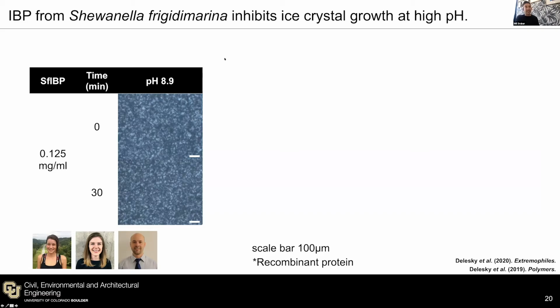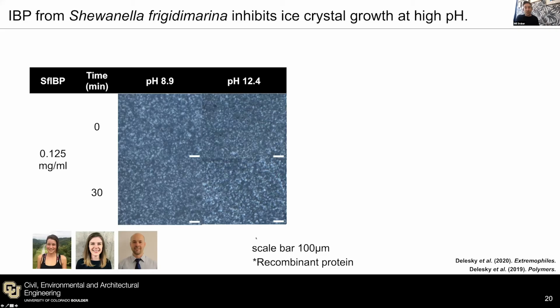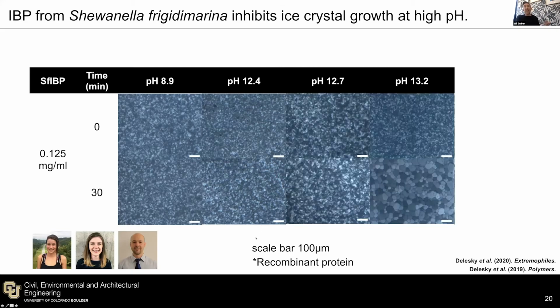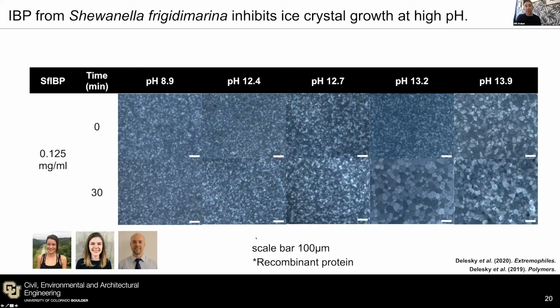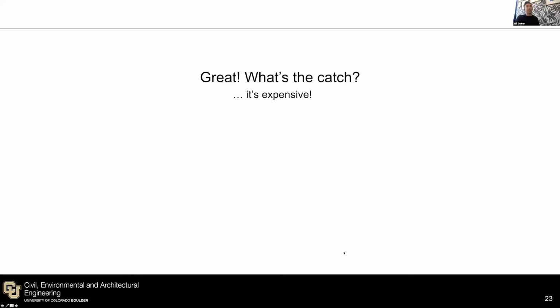We were exceptionally excited to see it maintained that activity at pH 12, pH 12.7, but then after we reached a certain threshold, what we proved in these papers is that the protein unraveled and then it disintegrated because the pH was so high. We also tested another ice-binding protein that we thought would be a little bit more effective in this calcium-rich, high pH solution, but we found the same thing. So, even though it worked up to pH 12.5, it's still expensive.